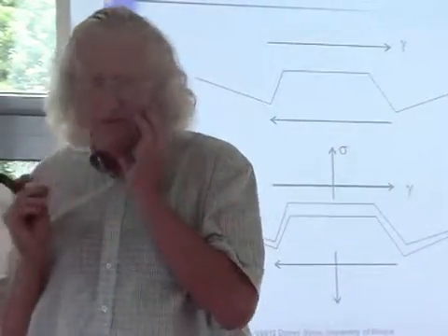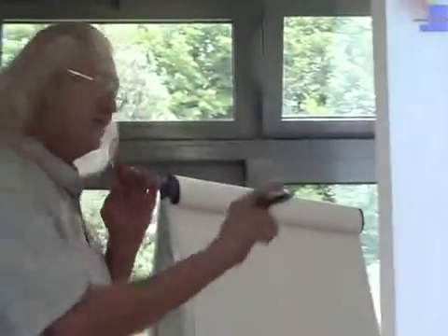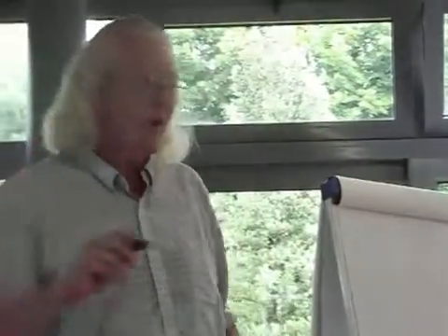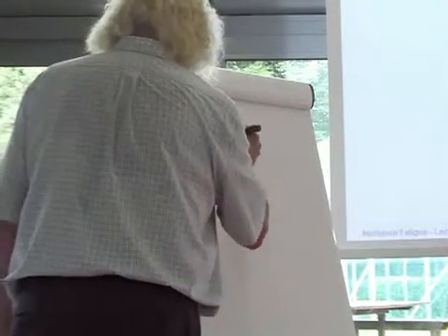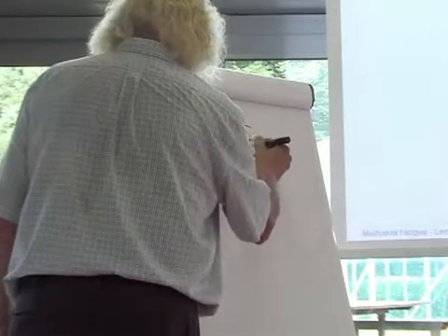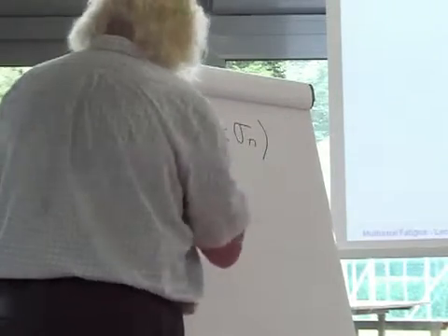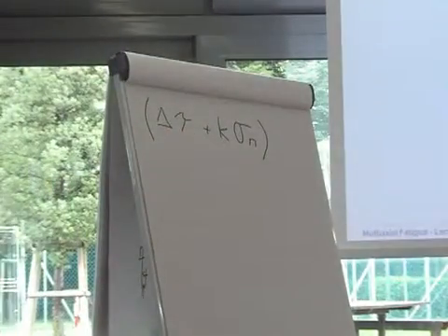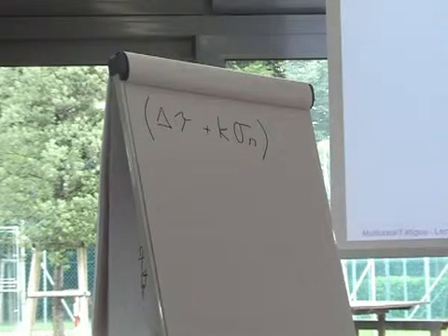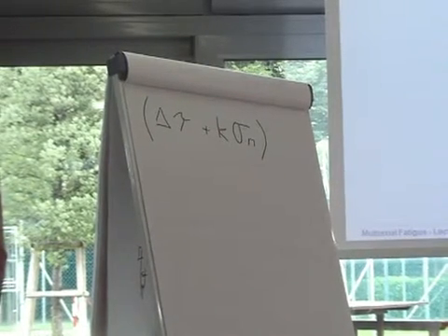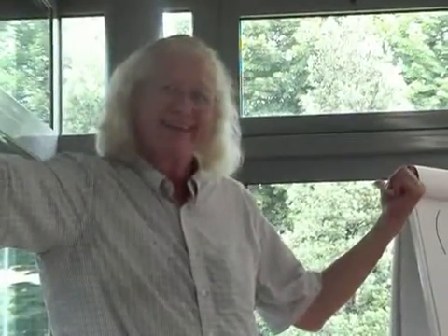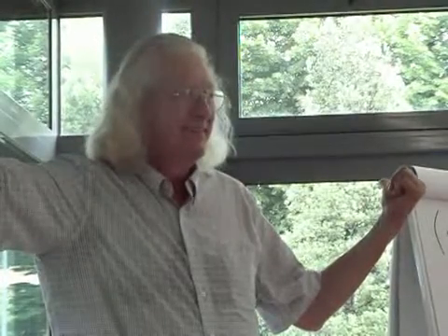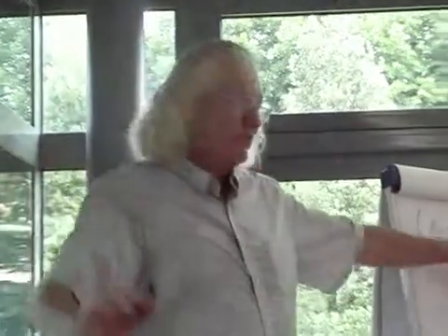I thought about this a while, and then it just dawned on me. Let's just look at Findley's model as an example, right? There's the shear stress plus, that's the parameter, right? Suppose the shear stress were 0 and the normal stress were high. What would the value of that parameter be? If the shear stress were 0 and the normal stress were high.